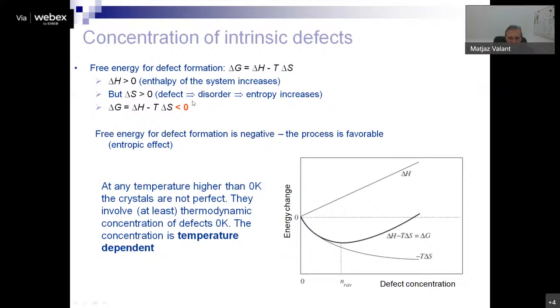So more defects, more disorder in the system, of course, and that means the entropy increases. And the increase in entropy is beneficial for the stability of the system, because we have this minus sign here. So if we take this now, this free energy with both terms, we can easily see that at some point, especially at the beginning, the term with delta S, with the minus sign here, is decreasing much faster than enthalpy is increasing. So we have initially the stabilization of the crystal coming to some equilibrium defect concentration where the system is the most stable. And then with a further increase in the defect concentration, we are destabilizing the system.